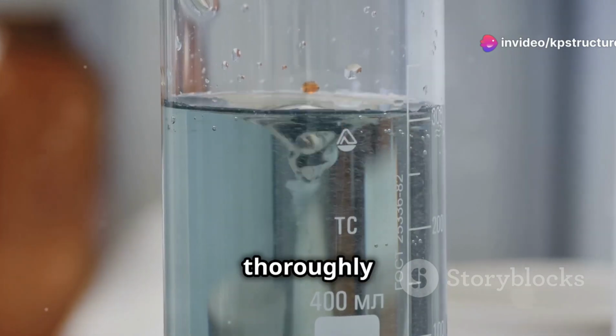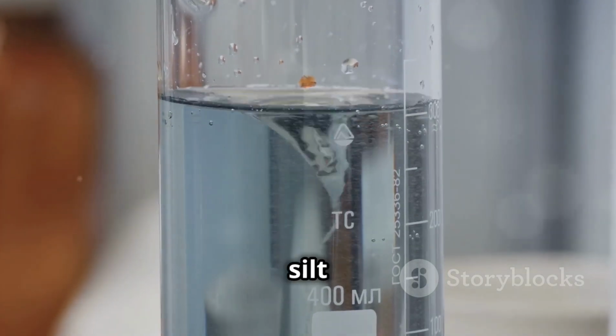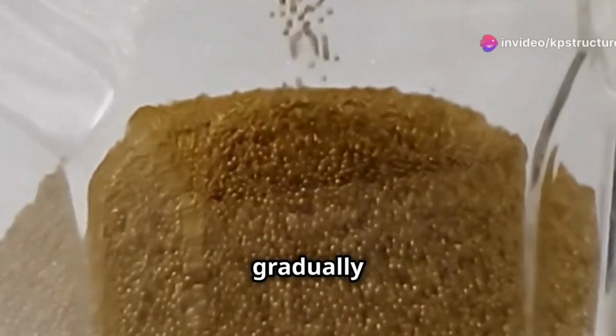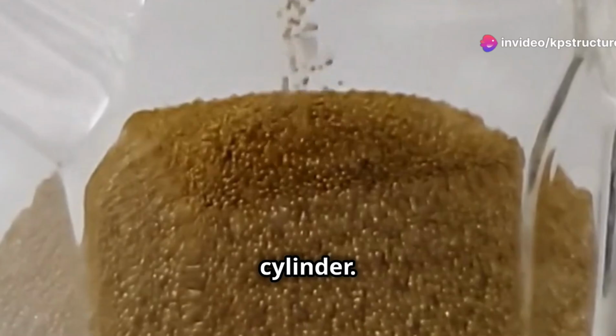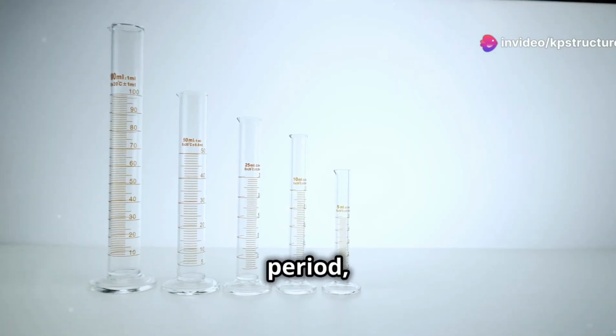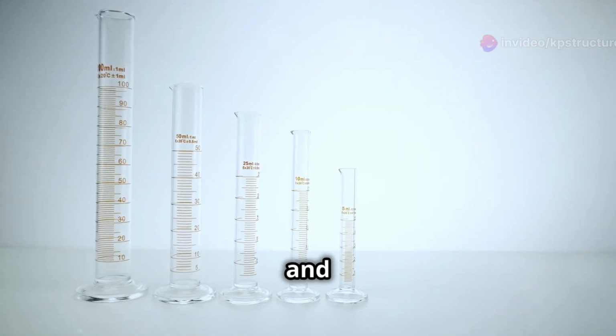Stir the mixture thoroughly to ensure even distribution of silt particles. Allow the mixture to settle undisturbed for at least 3 hours. The silt particles will gradually settle at the bottom of the cylinder. After the settling period, measure the height of the settled silt and the total height of the sediment.